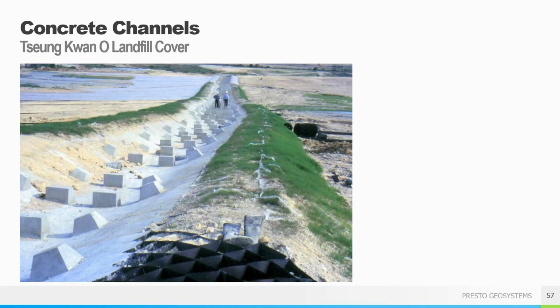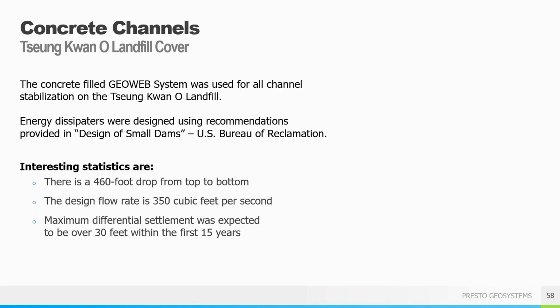Next up is a project that we did at a landfill in Hong Kong. And here's some of the specifics. Used at a Hong Kong landfill, it also incorporated energy dissipators, which were designed using recommendations provided in Design of Small Dams by the U.S. Bureau of Reclamation. This is a 460-foot drop from top to bottom with design flow rates of 350 cubic feet per second. And they also expected a maximum differential settlement to be over 30 feet within the first 15 years.